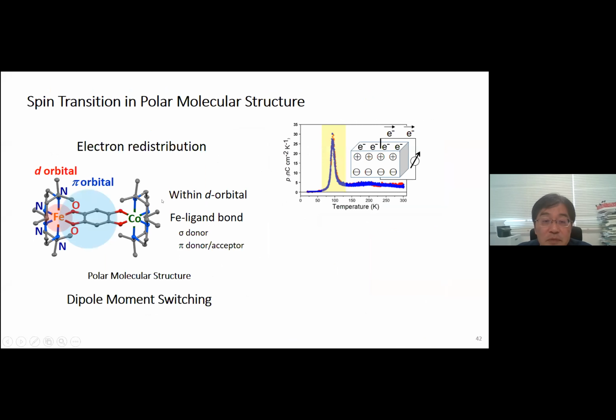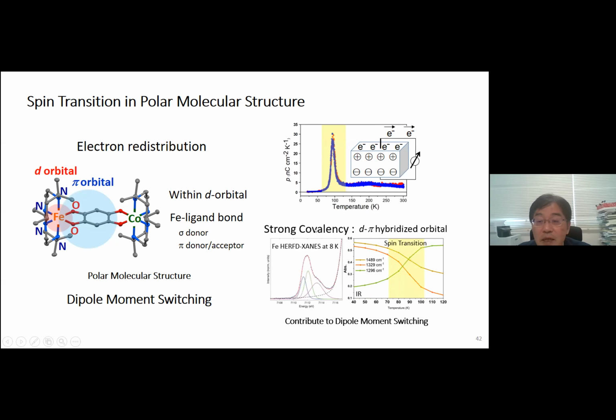And as I mentioned, spin transition is accompanied by electron redistribution, not only in the d orbital, but also in the iron-ligand bond. So this change induces a polarization change of this molecule, dipole moment switching. And furthermore, this compound has strong covalency, d-pi hybridized orbital. This strong covalency greatly contributes to the large change in dipole moment of this spin crossover complex.